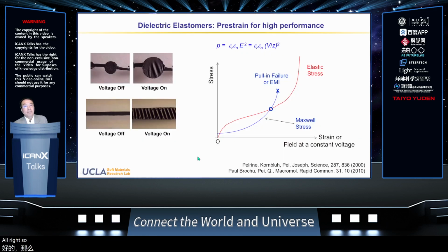All right, so the high performance from those dielectric elastomers, VHBs or silicones, is generally obtained from highly prestretched films. The image to the upper right shows the VHB when it's biaxially prestretched, so you will see the expansion in 2D. In the flat film, the area expands from circular to larger circular areas. And the lower left shows a film that was uniaxially pre-stretched in the horizontal direction. When you apply the voltage, the actuation is shown here mainly in the vertical direction. So pre-stretching makes a big difference and significantly improves the actuation performance.